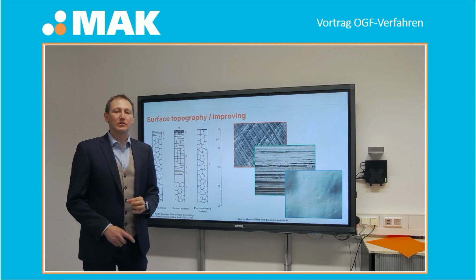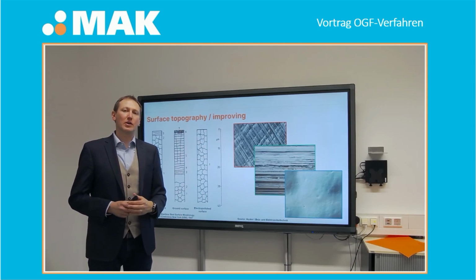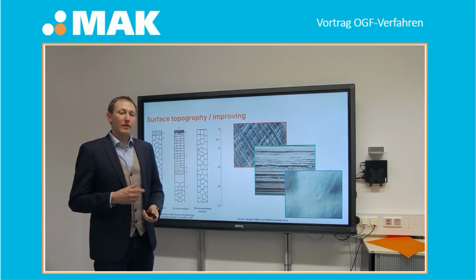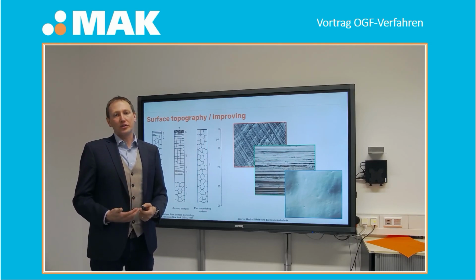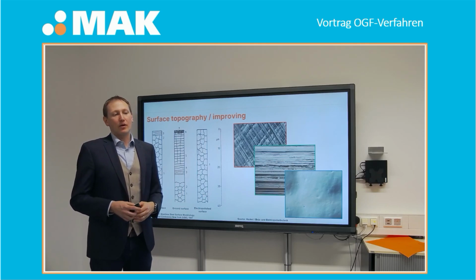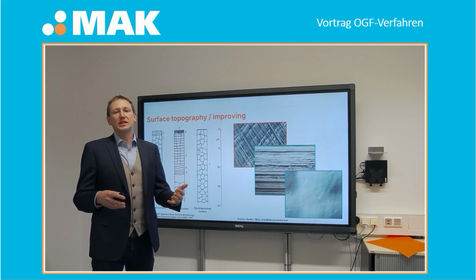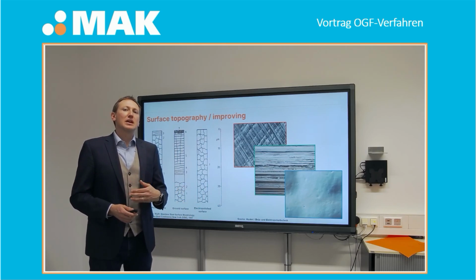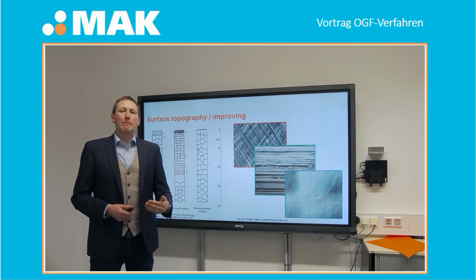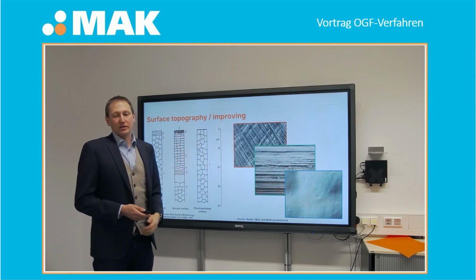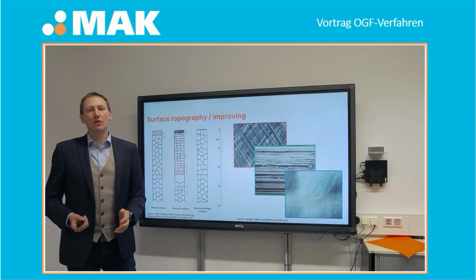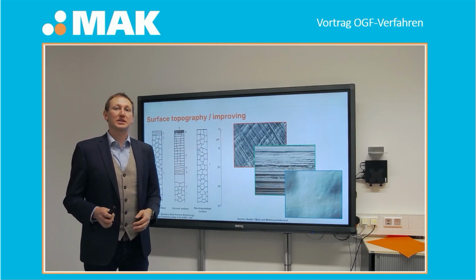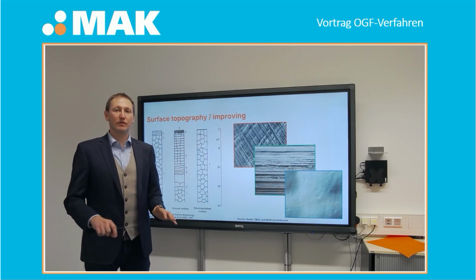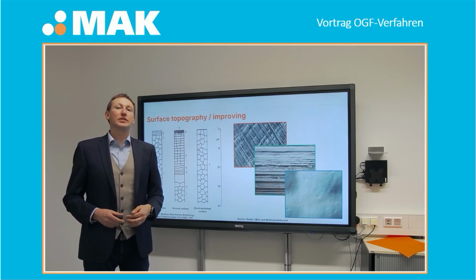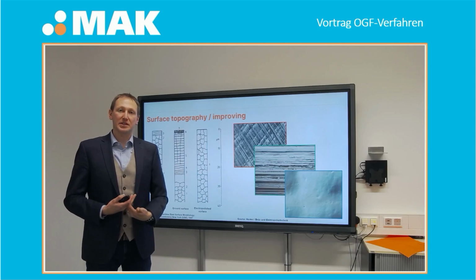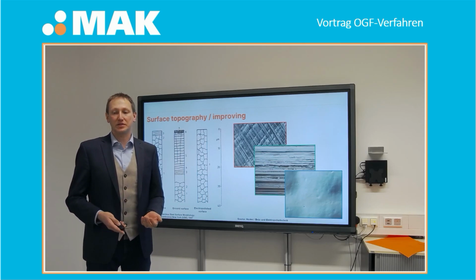But you have to take into account that the depth you can do electropolishing is limited. That means if you do a very harsh machining, a very harsh grinding on your surface, which is going to affect the depth of your material down to 40, 50, 60 micrometers, you may have some problems to remove everything of this Beilby layer by the electropolishing process itself. And what's the goal of electropolishing? Of course, the goal of electropolishing is to get a homogeneous structure, a homogeneous surface. And of course, it's also a goal to increase the corrosion resistance, so to reduce the effect of local defects on the surface.